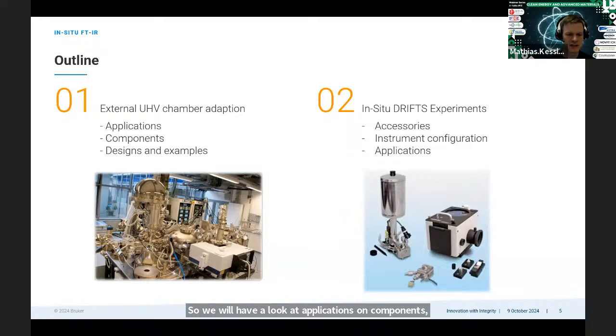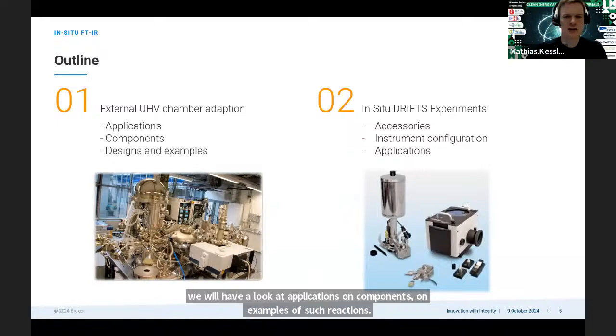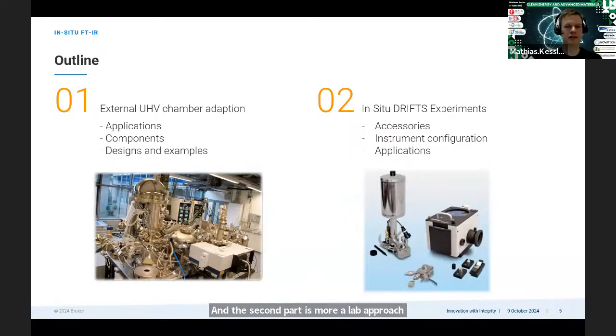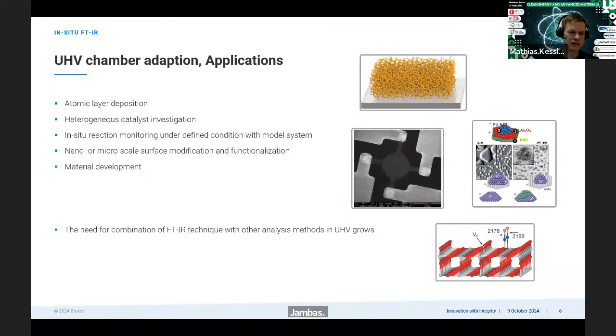And the second part is more a lab approach. So here we handle diffuse reflection infrared spectroscopy. And here we can use DRIFT accessories, which can be simply inserted into the sample compartment of an FTIR spectrometer. And then we can use reaction cells to create different temperatures and do our powder catalyst measurements inside of such reaction chambers.